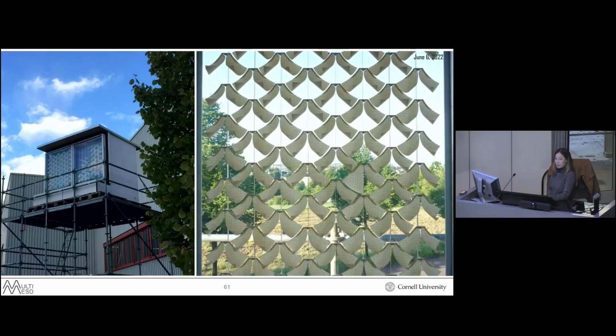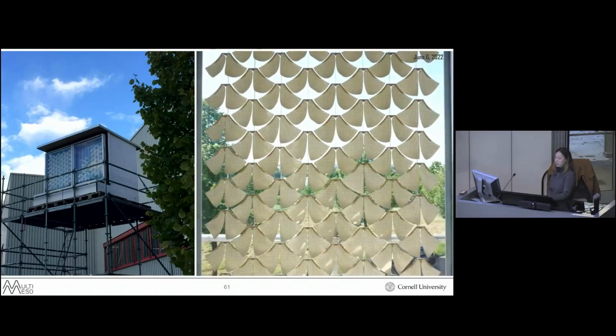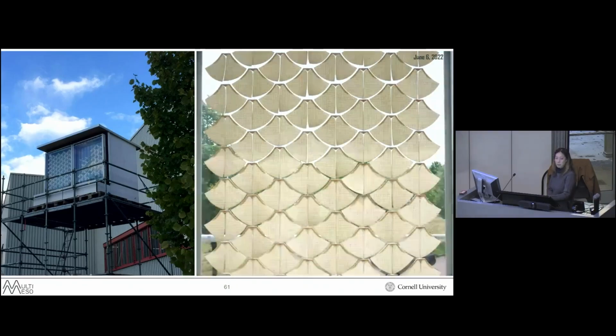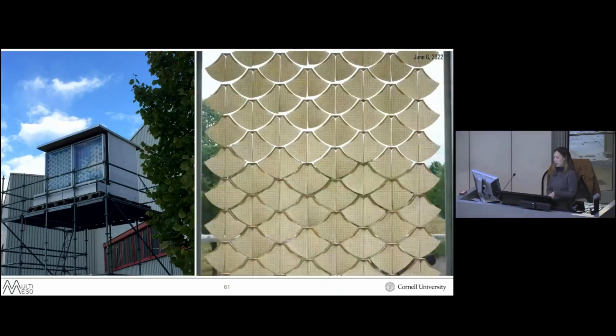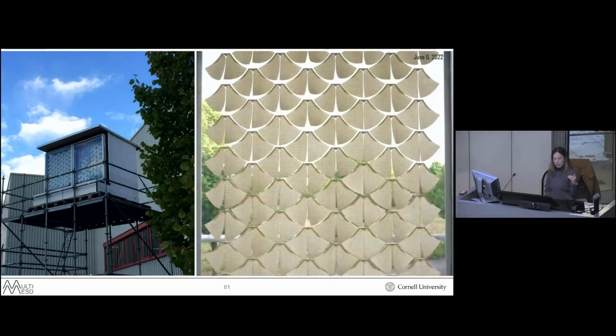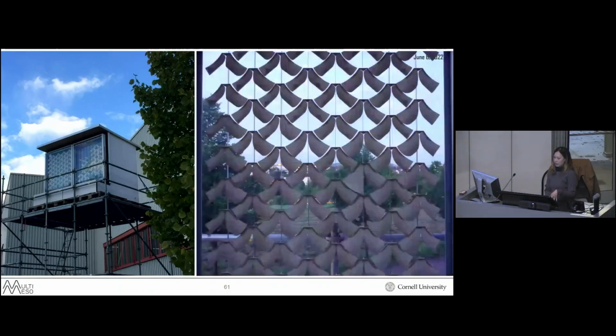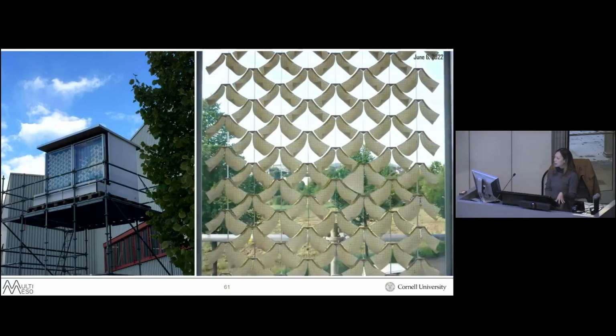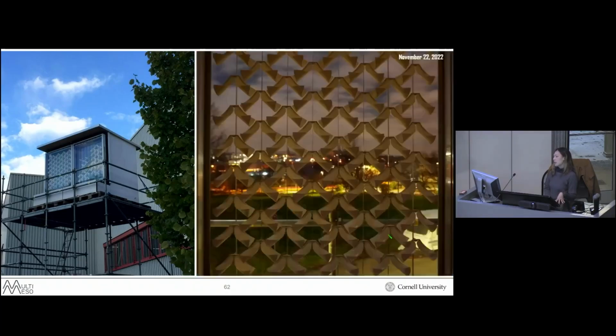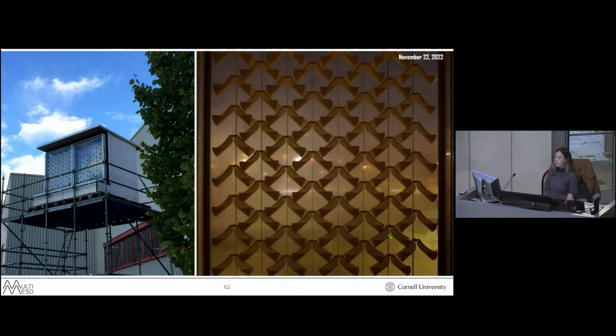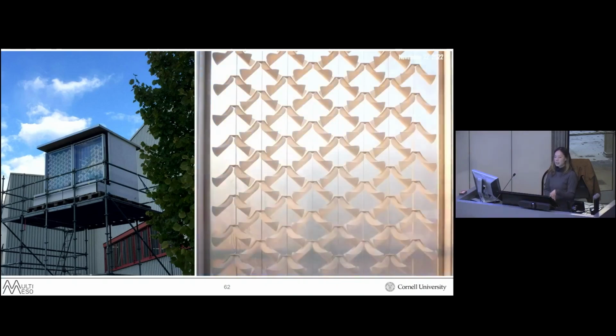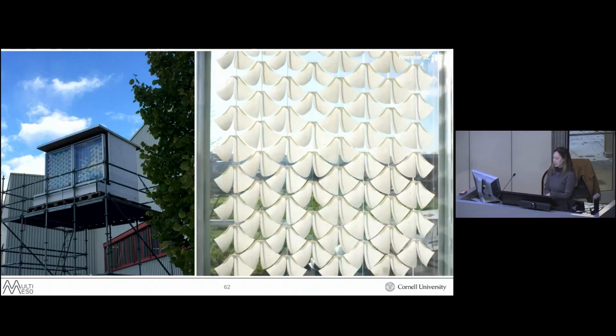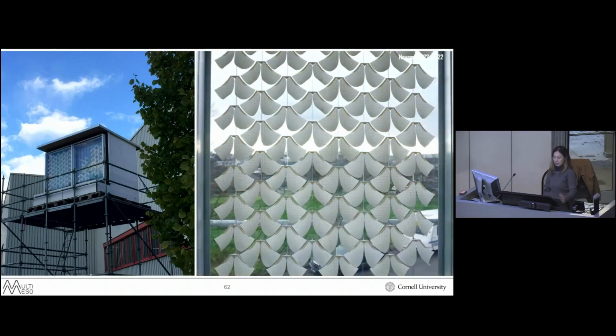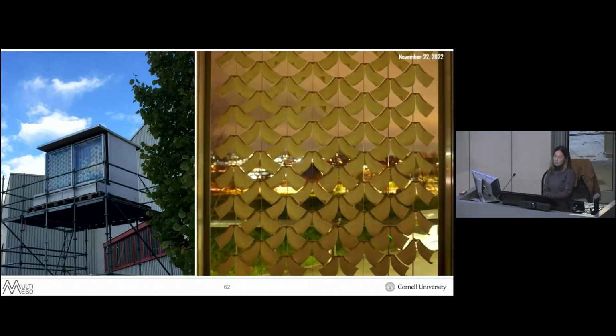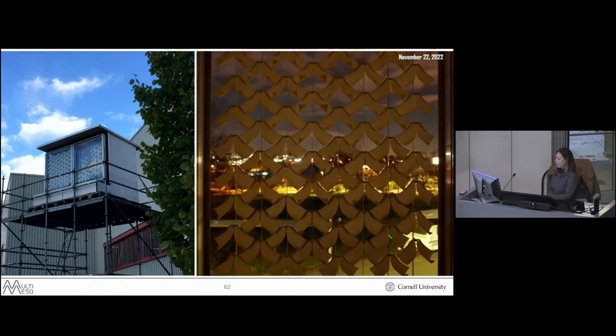And in order to test their performance under real weather conditions, I also built a mock-up of the facade in Stuttgart at the same height and orientation as the target building in Freiburg, in order to simulate the 4D printed elements in the full range of humidity, temperature, and UV effects of that type of climate, across all seasons for over a year.